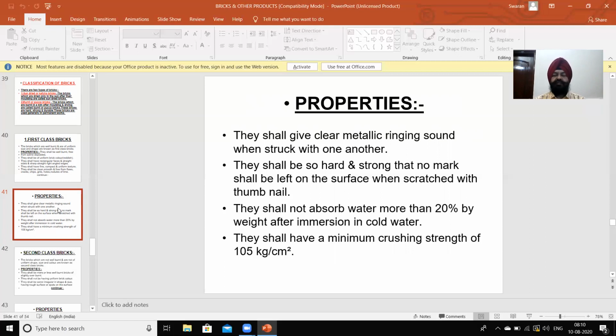So these are the main properties of the first class bricks: hard, strong, durable, uniform shape and size, free from flaws, grits, defects, nodules, cracks. They give clear metallic ringing sound when struck with one another. They are so hard and strong that no mark is left on the surface when scratched with thumb nail. They do not absorb water more than 20%, and the minimum crushing strength is 105 kg per centimeter square. So these are the properties of the first class bricks.